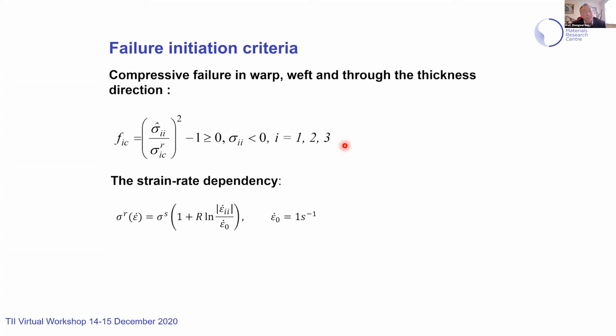And this is the strain rate dependency. Here we have sigma superscript S, which is the quasi-static strength, and inside the brackets we have some enhancement due to strain rate. The reference strain rate is 1 per second, but the current strain rate from impact or blast is variable. You can have maybe 100 per second to tens of thousands per second. So you can see this is quite a large enhancement. If you don't consider rate dependency, you wouldn't be able to simulate blast response especially.